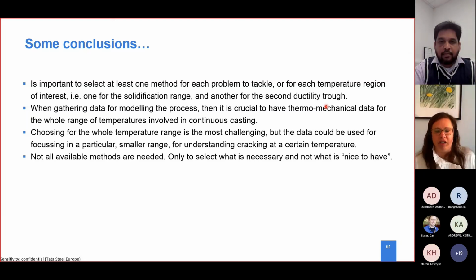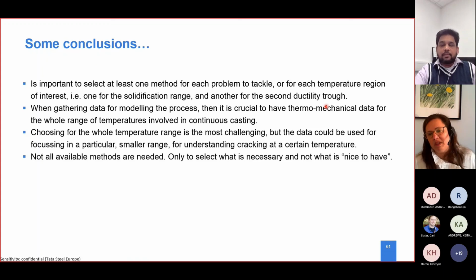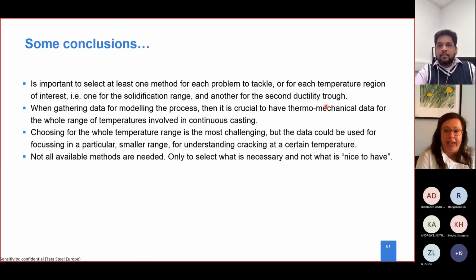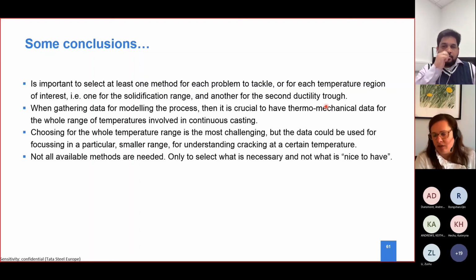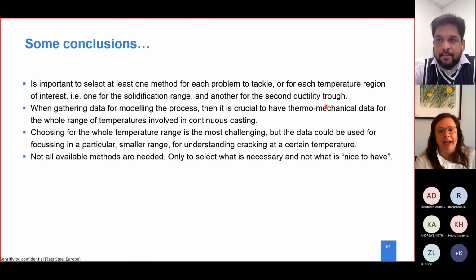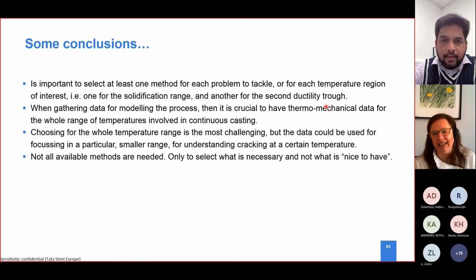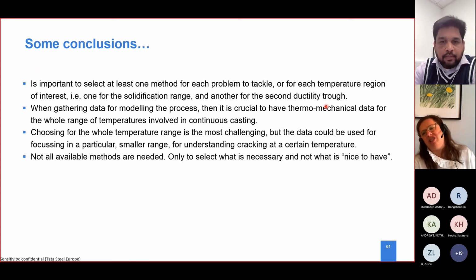Because for the modeling, for example, it's very crucial to have very good thermodynamic data. But the most challenging is if you don't have the data. If your problem is the second ductility trough, as I showed you, you don't always need thermomechanical data. Thermodynamic simulations to understand it are good enough. You could always improve it with tensile tests, or even what we are exploring now. I think a huge improvement is going to come with a 3-point bending test. Well, it's a 4-point bending test. But yeah, not all the available methods are needed, really. We need to select only what is necessary, and not what's just nice to have.